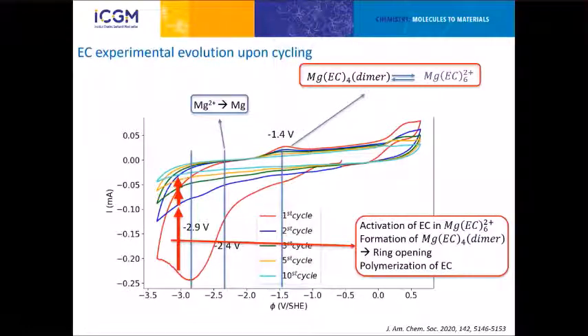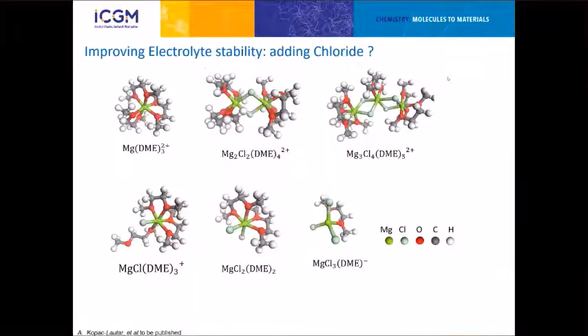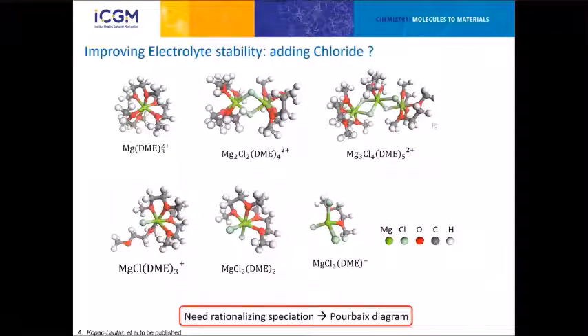break down. And ethylene carbonate could be stable, but the problem is it undergoes strong activation and you go to polymerization, and you are passivating your whole electrode by creating something polymer. So a good question is, how can we prevent that? One proposition was adding chloride to your electrolyte to form different kinds of magnesium chloride compounds that we compute. But to really investigate your reactivity, you need to understand the relation between potential and chlorination. So mostly what we need to do is a Pourbaix diagram for this kind of system.